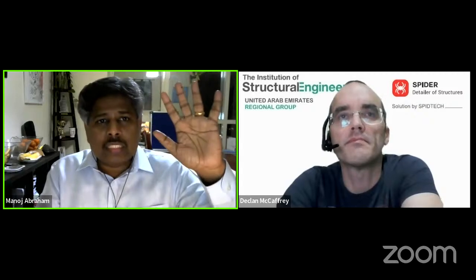Okay, thank you. And another question: what's the typical lifespan and general O&M strategy at the end of the first lifespan? All right, okay. Generally, these are reactive coatings. So as long as the coating is intact and without any mechanical damage, nothing is going to happen. It's not like after 10 years you have to recoat it. No, it doesn't happen like that. In fact, if it is a controlled environment internally, we even give lifetime warranties, right? On durability, we say as long as the structure is safe and sound, our coating will work. There's absolutely no problem. It's only when there are externals.